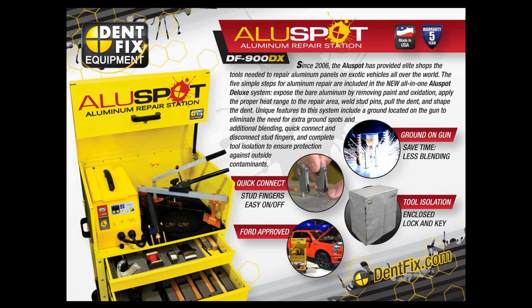Again, aluminum is softer than steel. The steel will not give of itself into the aluminum panel. But if you use that steel dolly on a steel skin, what happens is the fibers from the damaged skin will start impregnating themselves on the dolly, and then you take it over to an aluminum panel, and they'll start releasing themselves and being driven into the aluminum panel, causing that corrosion process to take place below the surface. You couldn't wipe it off. You'd have to do a severe amount of grinding.